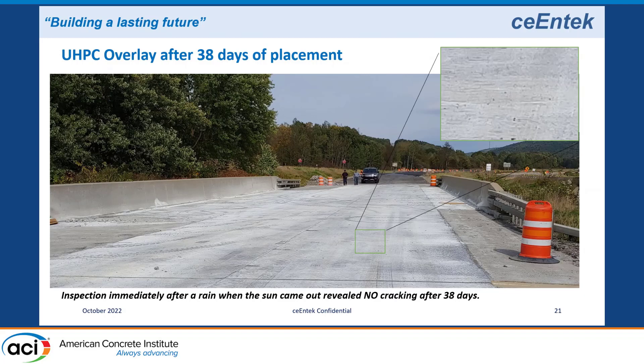I went back to this project repeatedly since the bridge was closed for an extended period. At about 38 days after placement, I returned the morning after rain. The sun had come out, evaporating all surface water — so any crack would show up as a black line on the deck. I walked the deck back and forth, up and down every side, and found zero cracks. That was good proof that the amount of shrinkage that actually occurred was quite minimal.